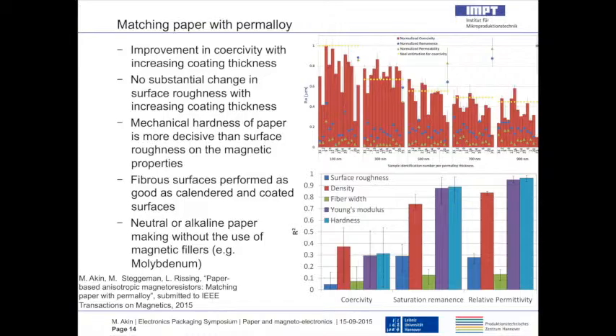And last, what we found from energy dispersive X-ray analysis, the good news, is that most of the papers that are commercially available are not made on an acid base because of the standards that were established in the last years, because a paper should last a couple of 100 years, even 1,000 years, if you buy a really good book. Comparing this with electronics on a 2-year cycle, buy and throw within 2 years, you see that once making something on paper, it might last forever. But also thinking about the fear that the acids in papers might attack your metallic or magnetic coating, that fear is not there, because most of the papers nowadays are made on a neutral or alkaline based solution.